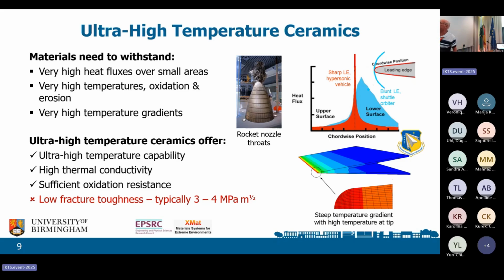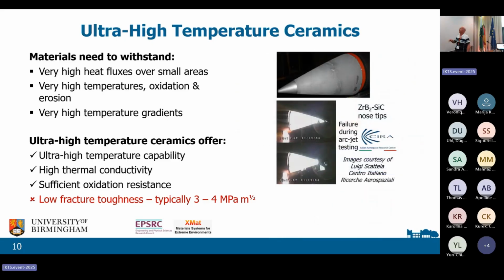So our ultra high temperature ceramics, they give us the temperature capability, they give us the thermal conductivity, particularly if you go for the zirconium and hafnium diboride. They give us the oxidation resistance just about, but fracture toughnesses are about the same as aluminium oxide, alumina, 3 or 4 megapascal root meter. That, and as you know, that's very low indeed. So thermal shock is a big problem.